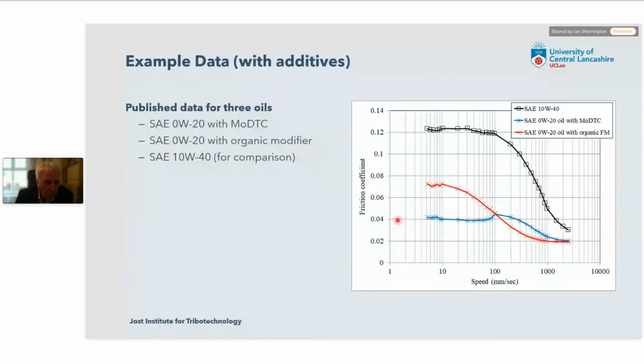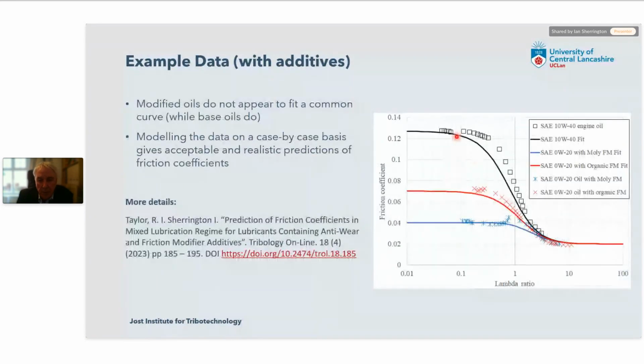How well does that work? Well, here's some published data from 3 oils, which we selected for our analysis. And here are the fit curves to those 3 oils. So you can see that the fit isn't perfect. There's only one set of data. And one of the key things here is it doesn't all collapse onto a single curve either, which is slightly inconvenient, but nevertheless still a lot simpler than addressing the problem by using surface modeling techniques.